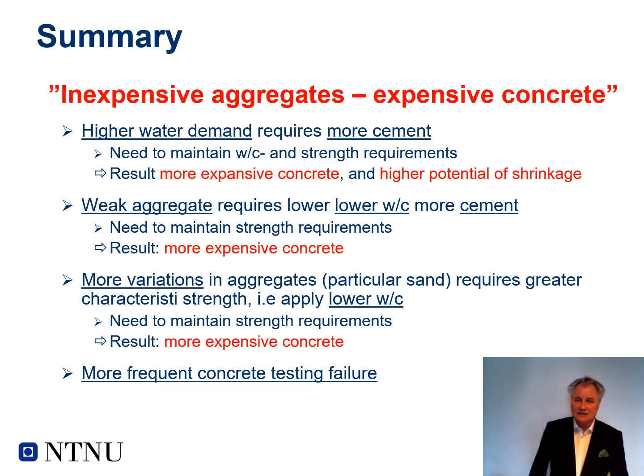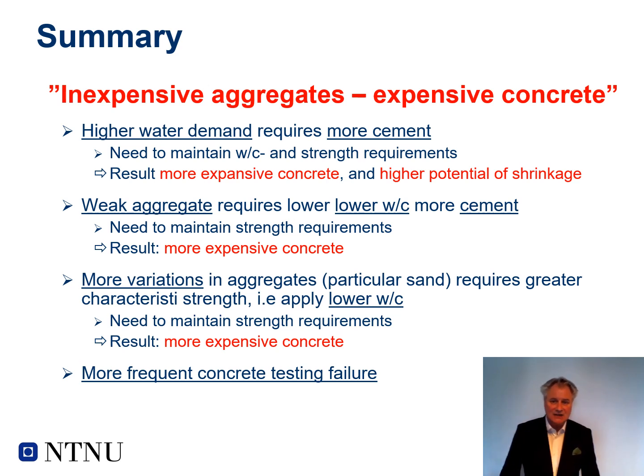So in a way, you could see that inexpensive or bad quality aggregates could lead to an expensive concrete. Because if you have a bad quality aggregate, for instance with inhomogeneous grading, bad shape, a lot of free mica and so on, you will get a higher water demand, which requires more cement to be added into your mix. And you need that extra cement to maintain the water-cement ratio and the strength requirements given for your concrete. So that will result in a more expensive concrete due to the higher amount of cement, and the higher amount of cement could also lead to a higher potential of shrinkage.